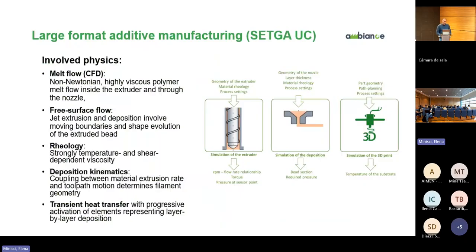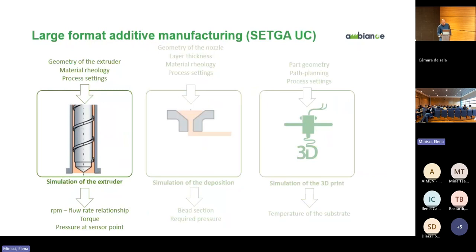We have a free surface flow. That means that the melt polymer exiting the nozzle is in contact with the substrate, but on the other side is in contact with the air. So it takes some special boundary conditions. Of course, everything is dominated by the rheology of the material, which is highly dependent on temperature and shear rate, and also the deposition kinematics that couples the extrusion rates and the motion velocities of the robot. And finally, very important is the heat transfer phenomena that determines the adhesion between the layers.